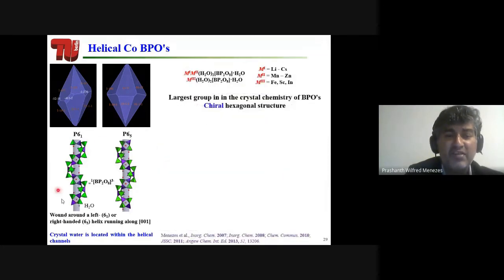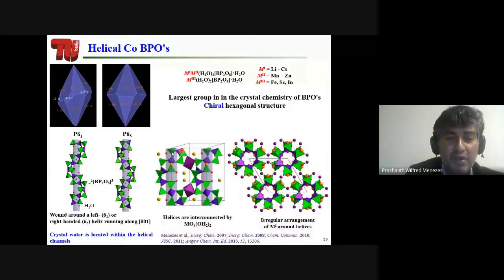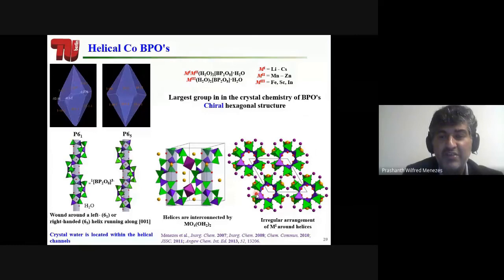And now how is this structure connected? As I already told you, these chains, or these helices, are connected to metal octahedra to form the complete structure. So if you look at the formula, we have lithium, and then we have metal, and then we have borophosphate anions. So these are the borophosphate anions. This is the metal octahedra, and the one in yellow color is the alkali metals. Very nice structure. You have a dense close packing of rods. You could see nice helices going down the structure.